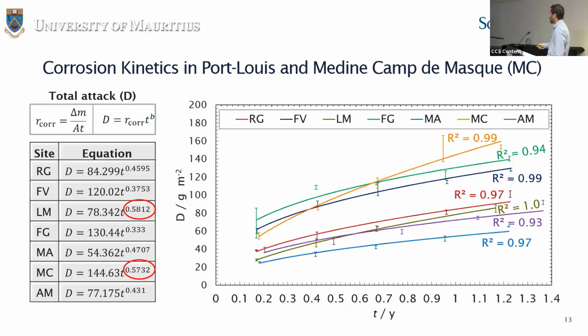A graph of total attack against time shows high R-square values for all the sites, which implies that the power law equation fits the data very well. As seen from the graph, there is an early stage where you have acceleration of corrosion, and then a longer stage where you have decreasing corrosion rate, most probably due to formation of stable rust phases.